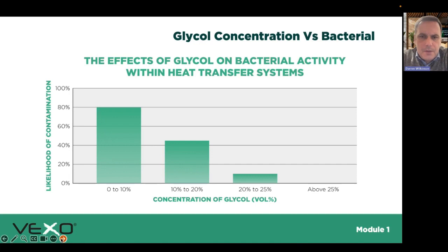So in terms of glycol concentration, as we're looking at ground source heat pump systems and other types of renewable systems that will require some level of antifreeze, some level of glycol, typically the industry considers anything above 25% volume by volume of dosed glycol antifreeze in a system biostatic. You shouldn't expect to see any issues really. But anything below that, as you can see from this graph, you run the risk that you're going to start feeding the bacteria. So rather than they can't flourish, they actually can flourish the lower the levels of concentration you go.